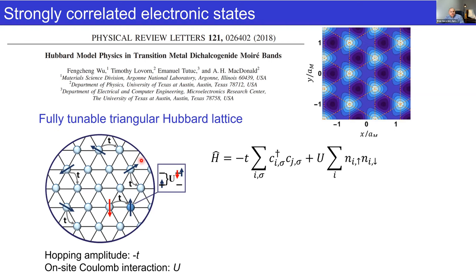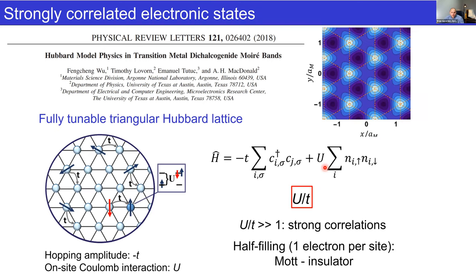So essentially it extends the tight binding approach, which describes carriers hopping between sites in a lattice with a certain amplitude T, to include an on-site Coulomb interaction. And this results in quite a simple Hamiltonian with two parameters, T and U. The ratio of U to T describes the strength of the correlations. So when this gets very large, then strong correlations emerge.